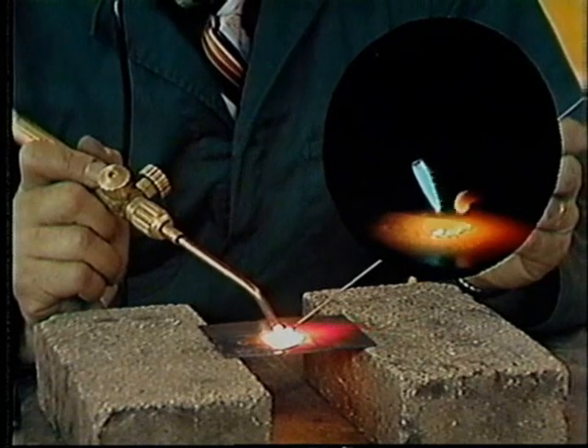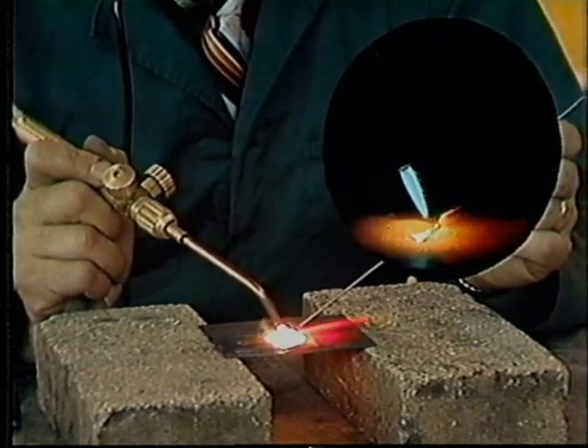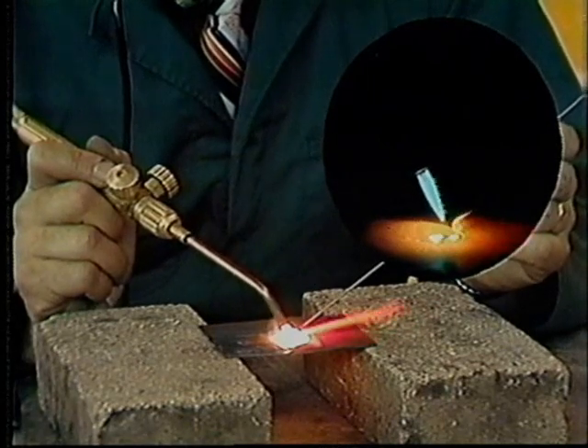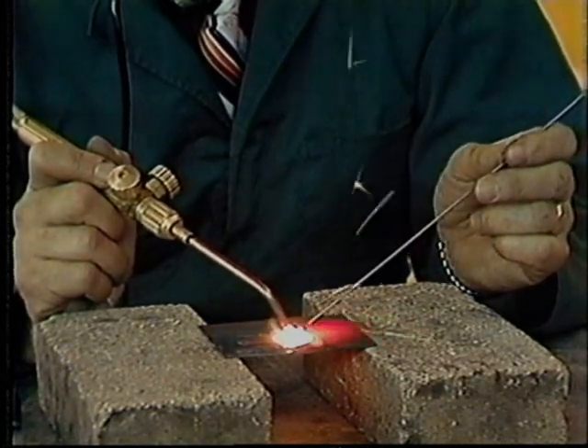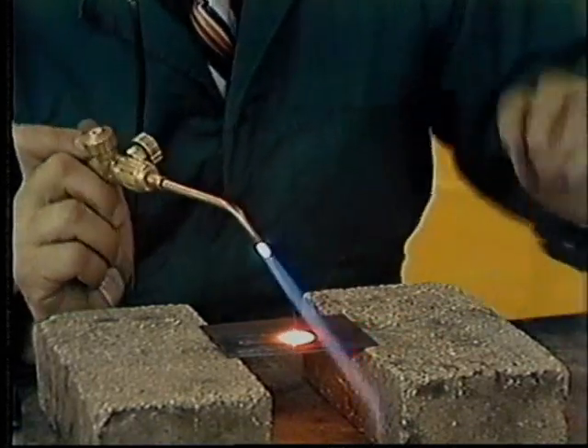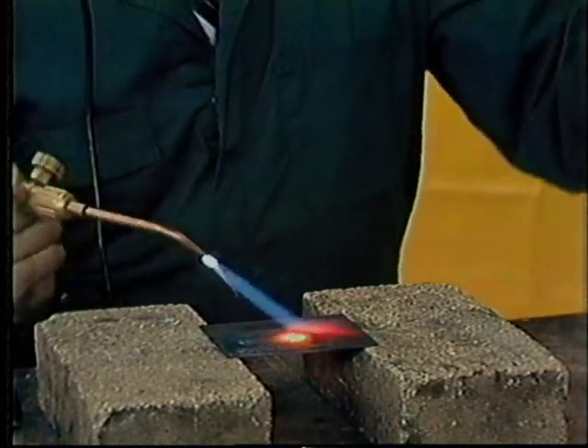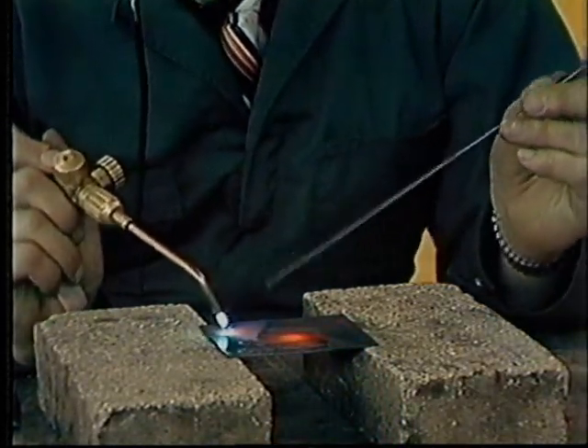Okay, is the height of the reinforcement critical? Yes, it is. If you get too much reinforcement, it acts as a stress riser. If you don't get enough reinforcement, you're going to have a weak joint. What is a stress riser and why is that bad? A stress riser would be a point of stress where you could possibly get a fatigue failure on it. I think that's probably a little beyond our discussion here, but it's important that you taper that bead smoothly into the base plate and that you allow the puddle to build up and have approximately half the base metal thickness. Okay, and that is the thickness that you should always go for, half of the base metal? I would say up to 1/8 inch thick material.